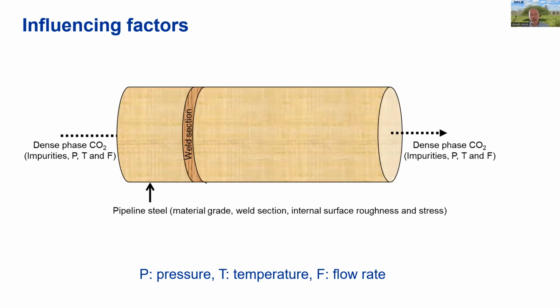So what types of things influence the corrosion rate in a pipeline? Well, there are two types of factors. Those that are associated with the fluid itself, so the level of impurities, the pressure, the temperature, and the flow rate, and factors that are associated with the material of the pipeline itself. So the grade of material that's used, whether it's stainless or carbon steel, whether there are welds there, the surface roughness of the material, and any stress, particularly residual stress from the fabrication of the material.